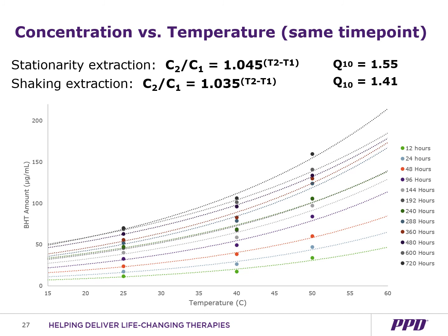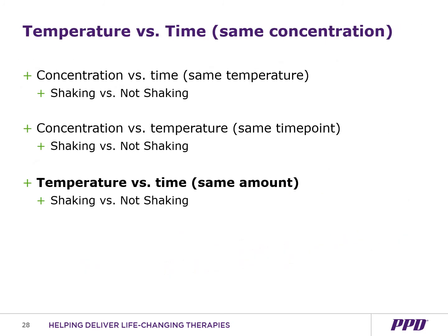We then back calculated to get the Q10 factor of 1.41 for shaking and 1.55 for stationary. The difference between the two data sets is within experimental variation and aids in supporting that shaking does not impact the extraction of BHT. And finally, we will look at temperature versus time using the same amount to see what effect shaking had on this calculation.